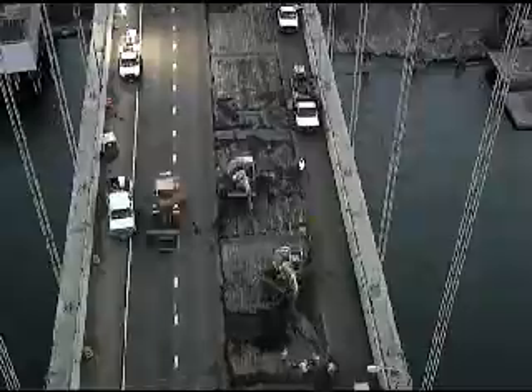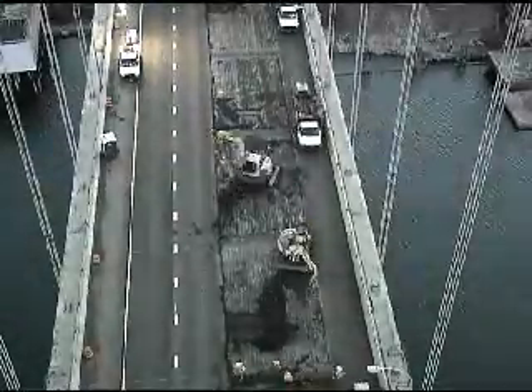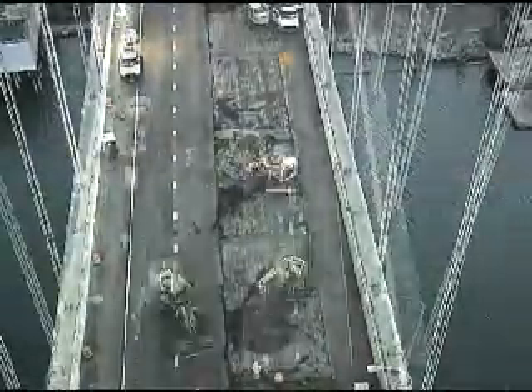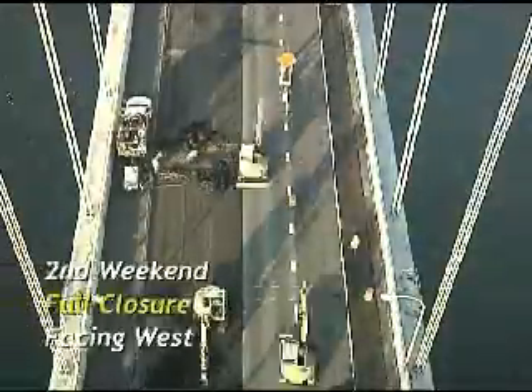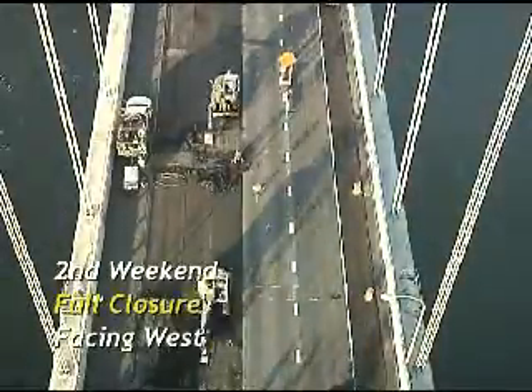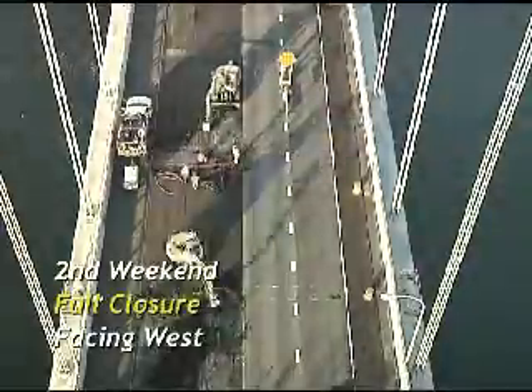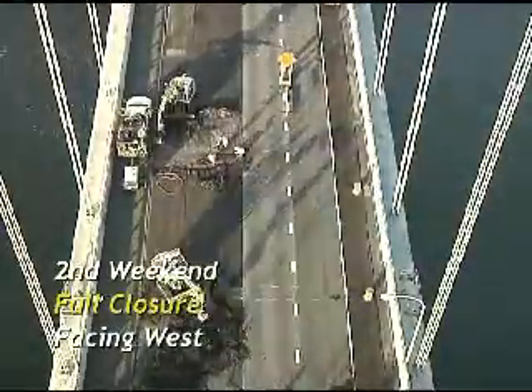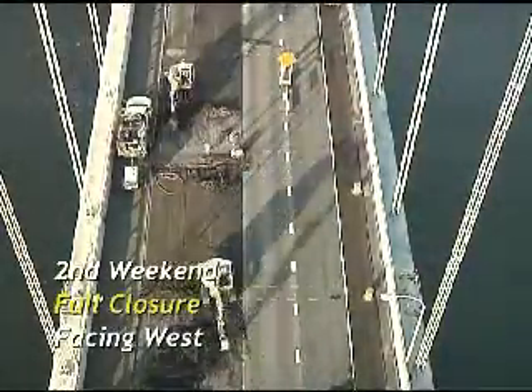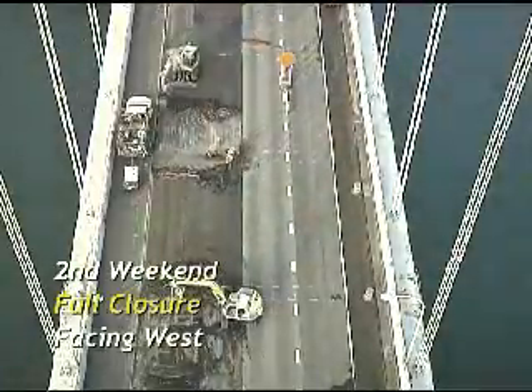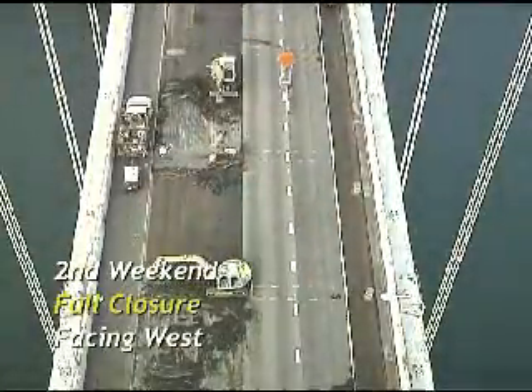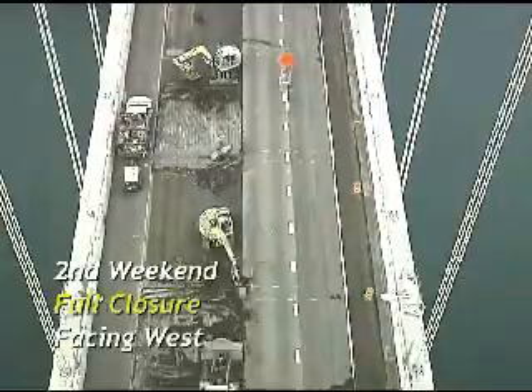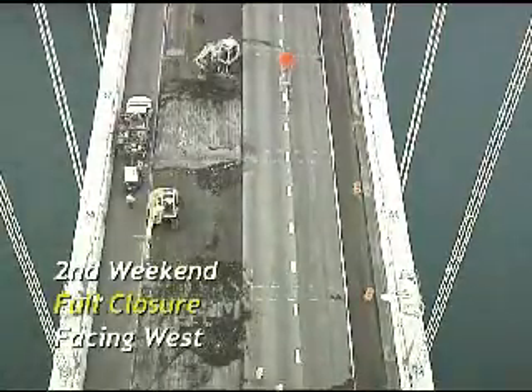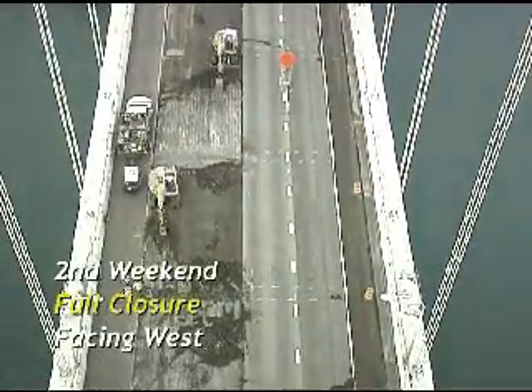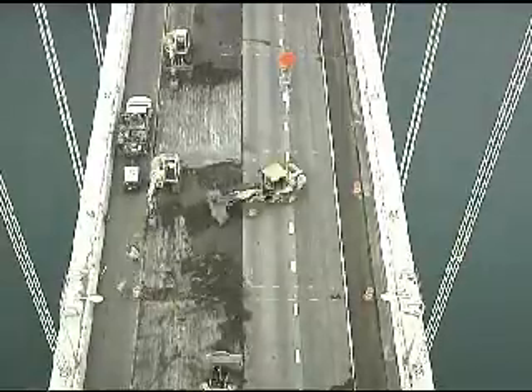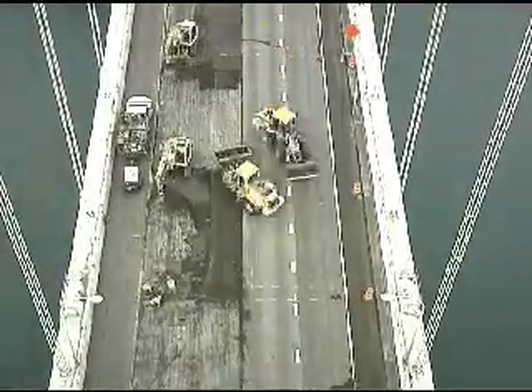The epoxy asphalt is very similar to regular asphalt, but with some significant differences. In addition to the oil or binder that goes into the aggregate to make asphalt, included with that is a two-part epoxy mix, a part A and a part B. The epoxy is a thermoset product that sets and gels with heat and time to create a very hard, strong, durable surface, much more durable than regular asphalt. The product for this project comes from a company called Chemco Systems out of California.